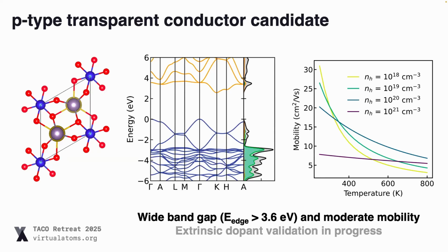And when we look at the mobility, which we calculated using AMSET, the mobility is pretty high. It's about 30 centimeters squared per volt second at room temperature, which for an n-type candidate is very low, but for a p-type candidate is actually up there with some of the best materials that we have already. So we did manage to find something, but 99.9% of things ended up getting filtered out.